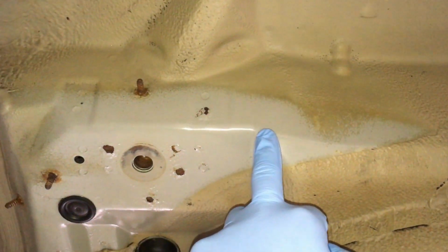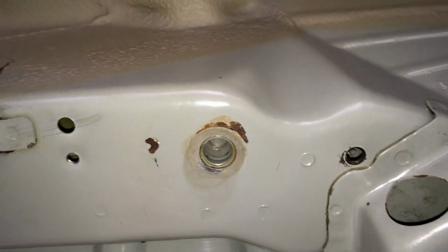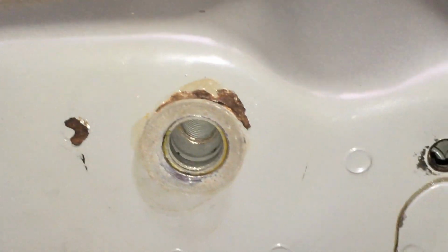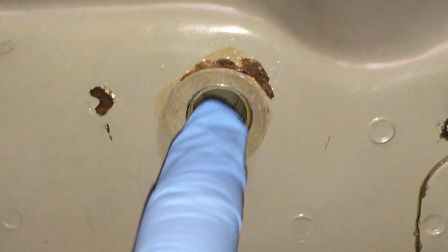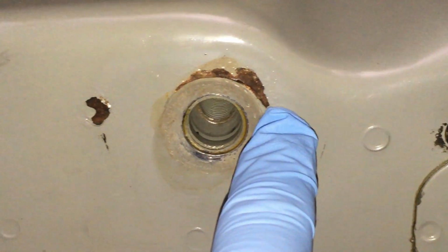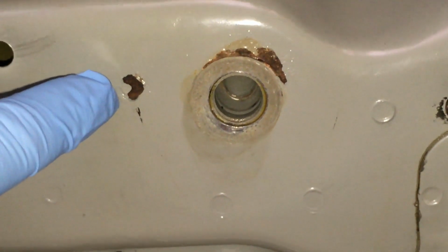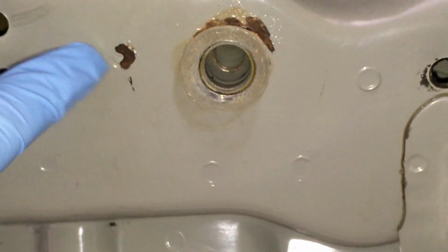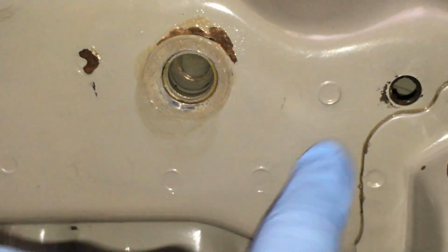We've got the right rear mounting point, which in this area looks absolutely fine, but if we zoom in on this area here on the fold of the floor, we've got a small crack just starting, which is a mirrored image of the other crack on that side, just not as long yet. Then the mounting points on the front, we've got a small hairline crack in a semicircle shape around this threaded mount here, going from about this side to about there. One spot weld which is flexed and not yet broken, but is showing signs of movement when you compare it to these spot welds, which are all perfect.